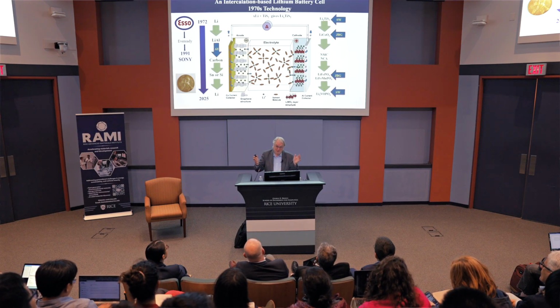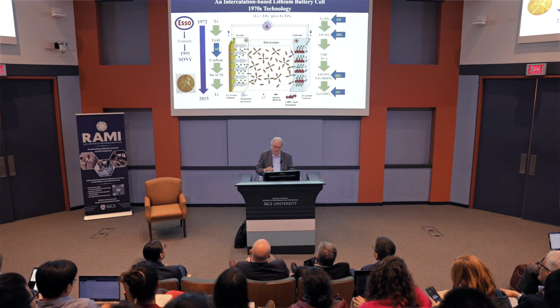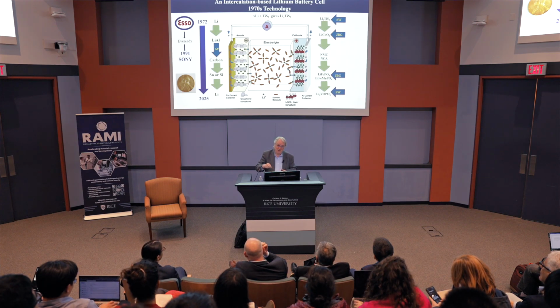So that's why we were looking at those. Tantalum disulfide was the best one. You can't use tantalum in a battery. So when we discovered these reactions, we switched to titanium, and that's what we used. It has a voltage of about 2.5 volts. John Goodenough was then at Oxford and read our papers. He was looking at lithium cobalt oxide for its magnetic behavior. And he said, hey, these have the same structures. I can do the same thing.